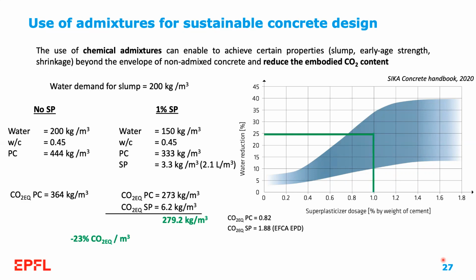If we take a typical concrete with a water demand for slump of 200 kilograms per cubic meter, and we decide to formulate this concrete with no superplasticizer or with 1% superplasticizer addition that enables me to reduce the water content by 25%, we can then compute the amounts of cement and superplasticizer that we are going to need. If we then take reference numbers for CO2 calculations and compute the carbon footprint of these two concretes, we can see that the use of the superplasticizer enables me to cut 23% of the CO2 per cubic meter of concrete just by applying this strategy alone.